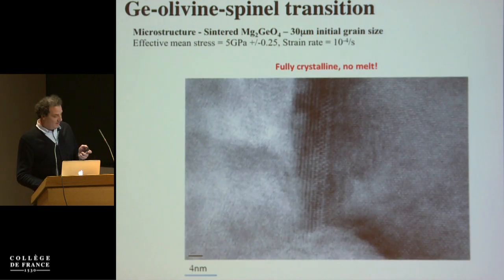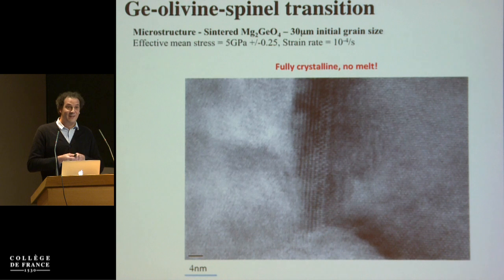If you look in very great detail, now this scale is 2 nanometers, a bit like in the images of Giulio. Here you see, and it's always amazing to me, the atoms being well lined up. So this is the lattice plane of the olivine, actually not of the olivine, of the germanium ringwoodite. And this is another grain, and you see that it is fully crystalline. We can't find any melt in this system. So there is something that we don't understand. In one case, we were at lower pressure, we break, we melt, and here we are at higher pressure, we break, we have larger slip, and we don't melt. So obviously, there is something going on.